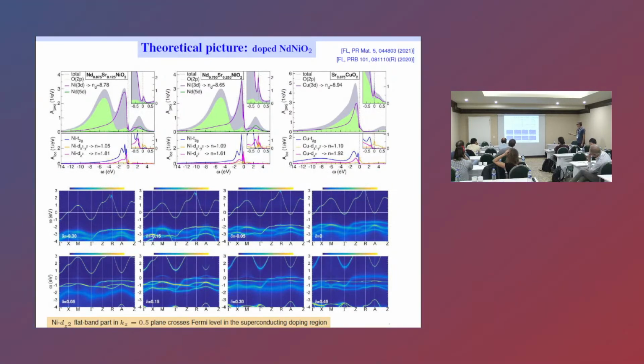And this is then confirmed in the theory calculation by the k-resolved spectra. And how does that cope with this angle-integrated situation? Well, with hole doping we shift this nickel d z-squared band that we were already talking about upwards over the Fermi level, into a flat-band-like regime, and this takes on all the holes, whereas the x-squared minus y-squared is more or less inert. It still has a local spin, and that goes together with the magnetic activity that we have seen in the experiment. It doesn't really like to get holes. It's more or less inert and remains a localized spin.